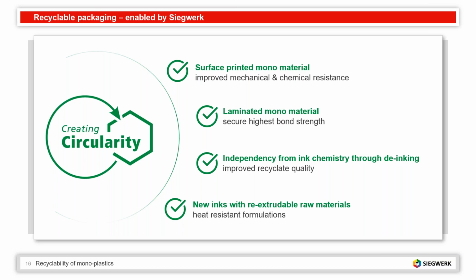So I would say there's a limited impact which we didn't test, but our target is more that we avoid the sticking. So that the heat window is only little influenced, because the polyolefin has to melt, but we avoid the stickiness, and we don't use up heat to seal. But we can check with our colleagues in South America. They should have the details. So if we get your contact details, whoever asked that question, we can follow up and give you more detailed information.